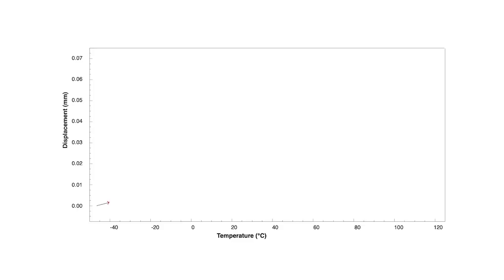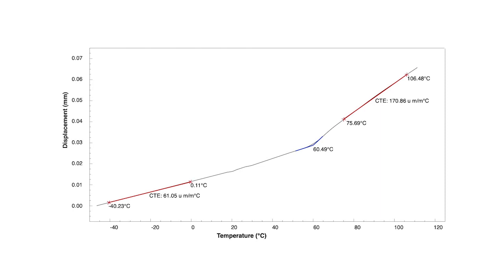The image we are showing here is a graphic result of a TMA. At the low temperature portion of this graph, on the left, you see the pre-TG CTE from -40 to 0 degrees C. As the temperature increases to the right, we see an inflection point on the graph at about 60 degrees C. This is the TG. Below this temperature, the polymer is considered a rigid polymer, and above this temperature, the polymer is a soft, pliable polymer. To the right of the TG, you see the post-TG CTE, which is higher than the pre-TG CTE. It is important to understand where the TG of the polymer is relative to your operating temperature range to reduce component stresses that occur in this thermal transition.